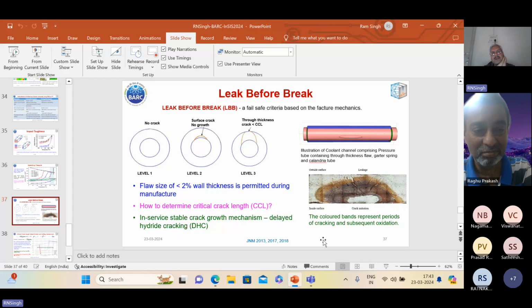Right now, the dispute in the international community is whether the DHC process is a precipitation-first process or a diffusion-first process. One group of people suggests that when the load is applied, first hydrogen diffusion takes place near the crack tip, and once hydride is precipitated, then crack growth takes place. Another group believes that as soon as the load is applied, hydride precipitates, and when it precipitates it sets up a concentration gradient, because of which hydrogen migration takes place. So in both cases, both diffusion and precipitation are required, but which one is first? Accordingly, model parameters change. Right, so it's path dependent.